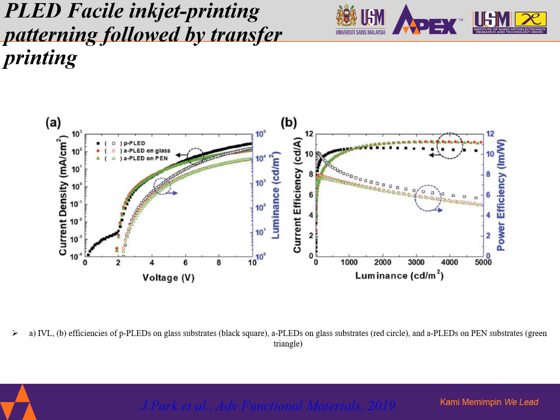These are the figures that show the device characteristics of P-PLED on glass, defined by a black square, and A-PLED on glass, red circle, and A-PLED on PEN, which is a green triangle. So all of these devices showed almost the same turn-on voltage, which is around 2.2 volts, defined at 1 candela per square meter. Current and power efficiencies at 1000 candela per square meter were also similar, which is around 10.4 to 10.6 candela per ampere, and also 7.1 to 8.0 lumen per watt.